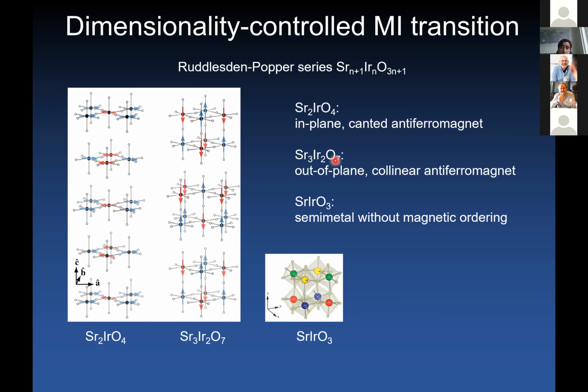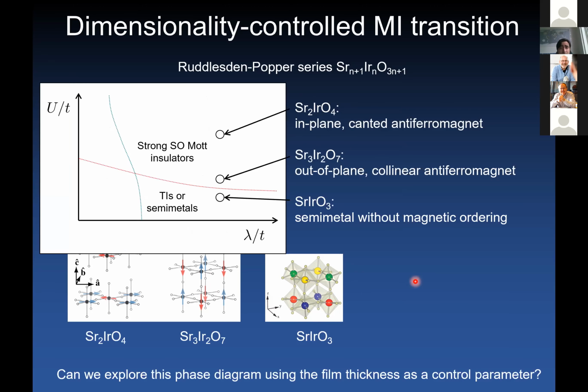When you instead go to the 327 phase, you still have a Mott insulator, but now the spins point out of plane, so they form a collinear antiferromagnetic state. And if you go to the three-dimensional limit of the 113 strontium iridate phase, you find a semi-metal that shows paramagnetic behavior in the bulk. And so in a sense, using these bulk materials, you can already navigate this phase diagram in which you vary the strength of U over t, so the relevance of correlation with respect to the bandwidth of the materials, and you can navigate this Mott transition.